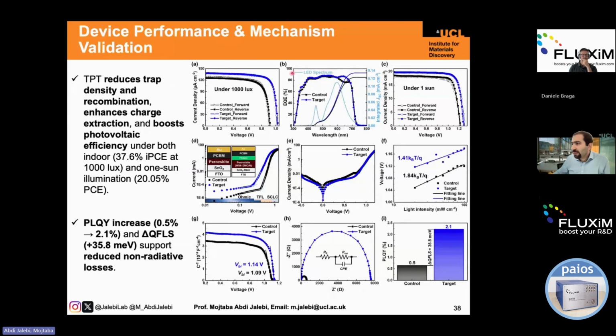All right, so now to better understand the performance of the device, we actually make the solar cell out of it, and we measure the wide bandgap solar cell. We measure it under one sun. We also measure it under indoor lights. We have utilized this 1000 lux as a standard in the literature. And you can see that the target one is significantly enhanced in terms of both VOC and JSC. And overall PCE has been enhanced under indoor light conditions for the target.